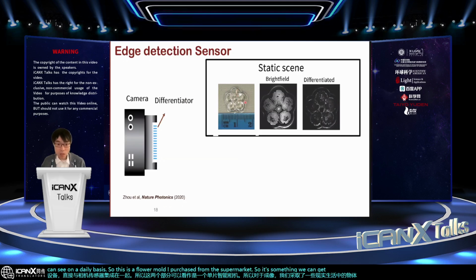And as we image this flower mold using our camera, this is what we see. You can see that now those boundaries of the flowers get clearly revealed. And then we can also see the defects on the mold, which are not very visible otherwise. And that means that our camera can also potentially be used in the food and defect inspection industry.